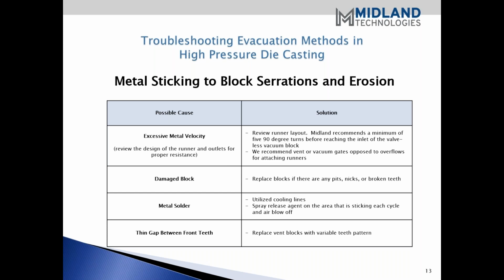If you solder, we mentioned solder down below, that problem, when it does come up, the best means to completely remove it is to polish. In those instances, we do offer coatings. It's important for people to remember that there are two different types of coatings: surface coatings, and coatings that penetrate the steel. If you take even a wire brush in some cases with a surface coating, and certainly with a stone, if you go to work to remove solder buildup on that block, you're also going to remove the coating.